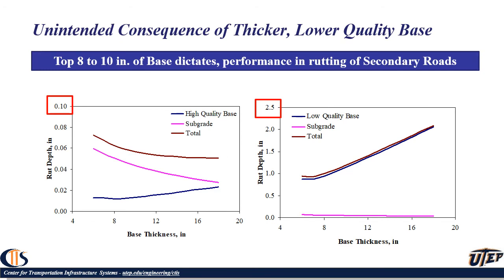One thing that we learned very quickly is an unintended consequence of using thicker, lower quality base. If you use empirical designs like the AASHTO 1993, if you make the base thicker, you're going to control the rutting. What I'm showing you over here is the same pavement structure, one with a high quality base and the other one with a low quality base. And we are looking at the variation of the rutting with the thickness of the base, from 4 inches of base to 20 inches of base.